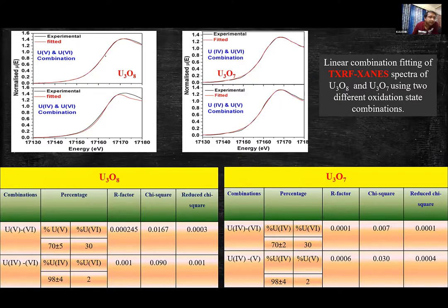And after fitting, not only can the Athena software fit and tell the combination, but it can also determine the percentage of the different species that are present. So by fitting this spectra, it was seen that in U3O8, uranium is basically present as uranium +5 and +6, with 70% uranium +5 and 30% uranium +6. And this data also agrees with the theoretically predicted value, that is 66 and 34%.